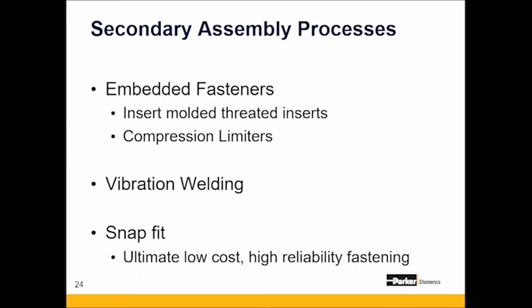And this is the opposite of what people are doing with die cast parts. They're usually die casting a part and then secondarily either drilling or tapping or both. Another technique that's used quite often is welding. Virtually any type of welding that's done with plastic, you can do with conductive plastics. So, you can use vibration welding, hot plate welding, UV welding, laser welding, and ultrasonically install parts together.